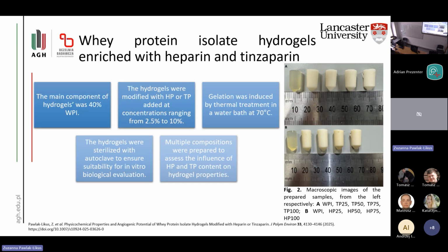And here on the right, we have a picture of the samples that we made. The main component of our hydrogels was 40% WPI, and the hydrogels were modified with heparin or tinzaparin, added at concentrations of 2.5, 5, 7.5 and 10%. The gelation of those samples was induced in a water bath. We set the water bath at 70 degrees Celsius, and we left our samples in it for around 5 minutes.